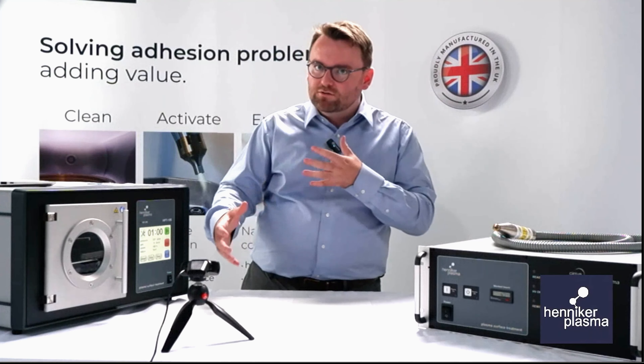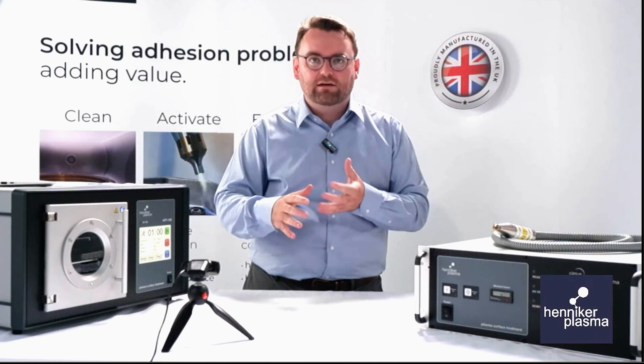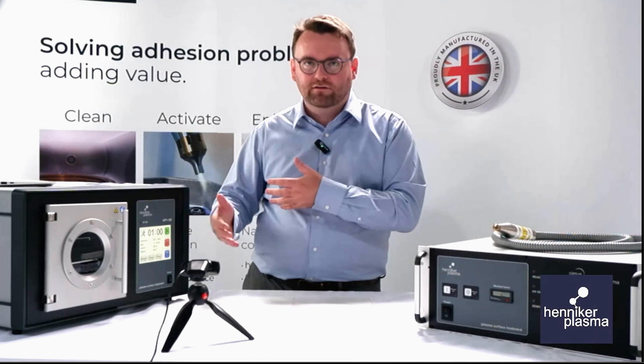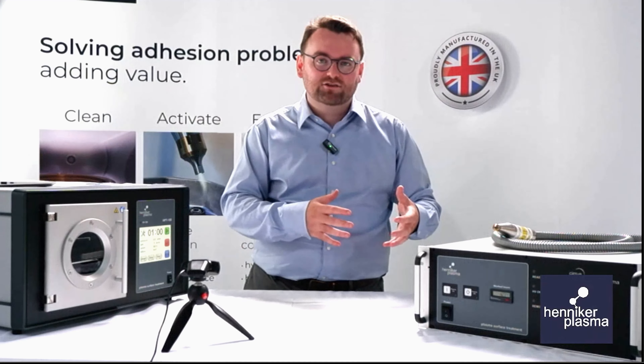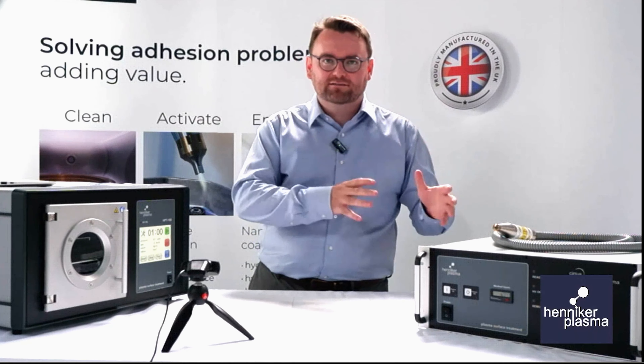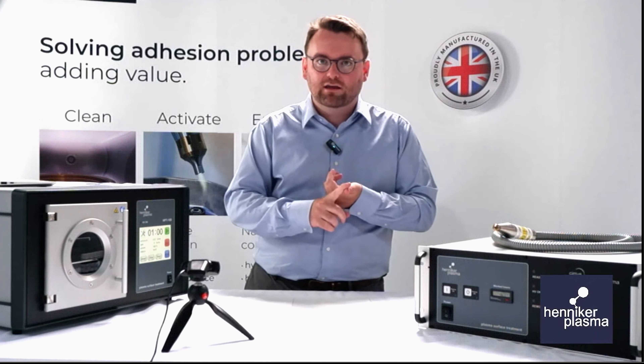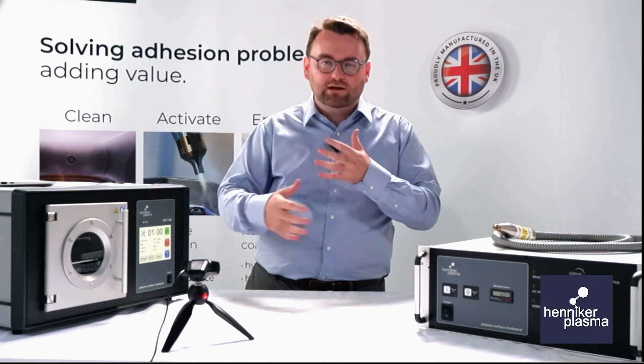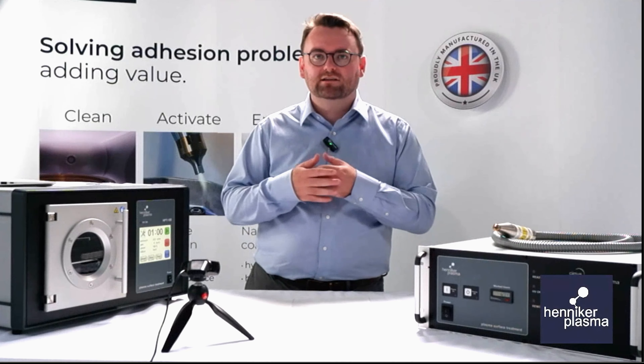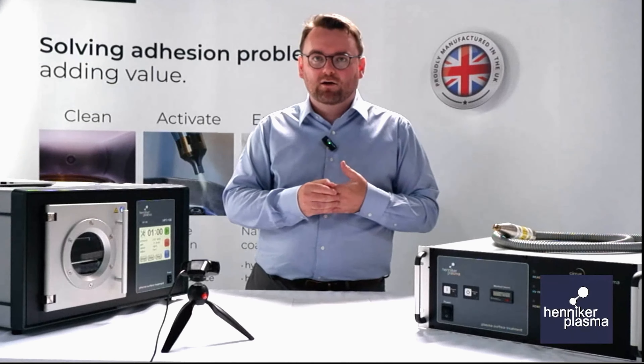The major barrier to using plasma is twofold. If your part is already too heavily soiled — for instance, if there's really thick heavy grease on there — we normally suggest doing a pre-wash before plasma treatment, which will give you perfect results every single time. In terms of plasma activation, it works for every material, however certain materials it will work better for than others. For carbon composites, PEEK, PTFE, polypropylene, and polyethylene, these are all great materials. If you activate these, the activation typically lasts for many days, giving you a lot of flexibility with processing — so if you plasma treat a whole batch and then wait an hour or two before painting, that's absolutely fine.